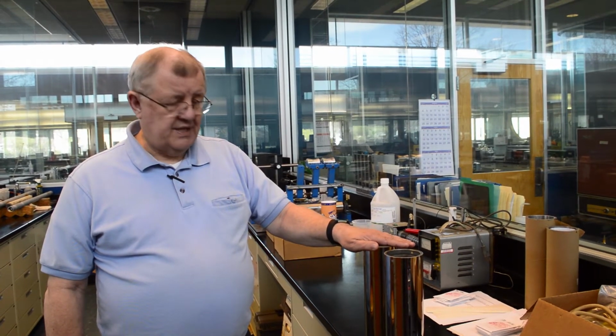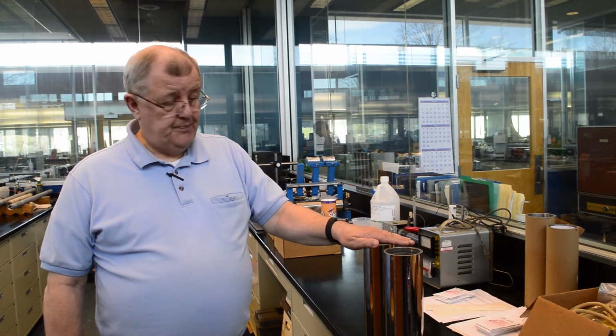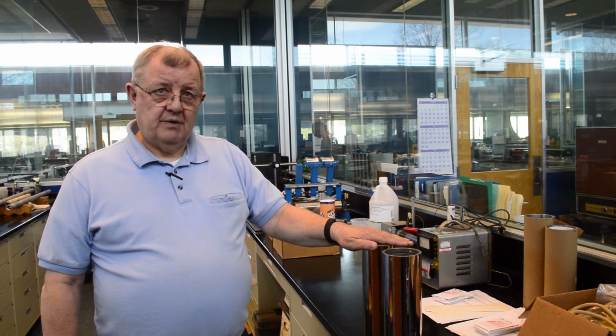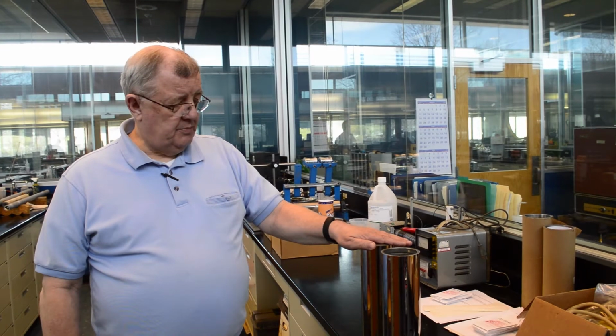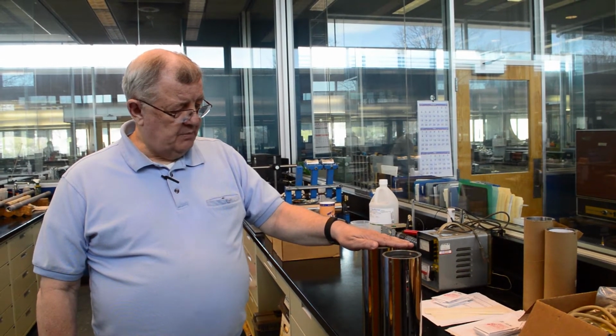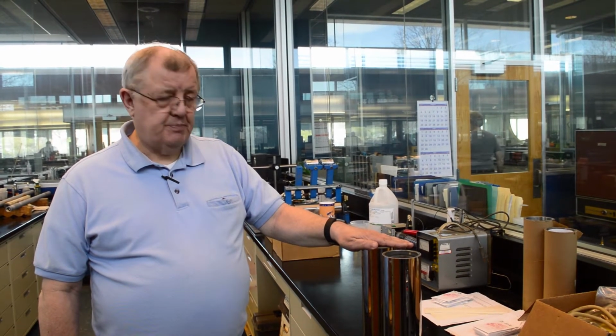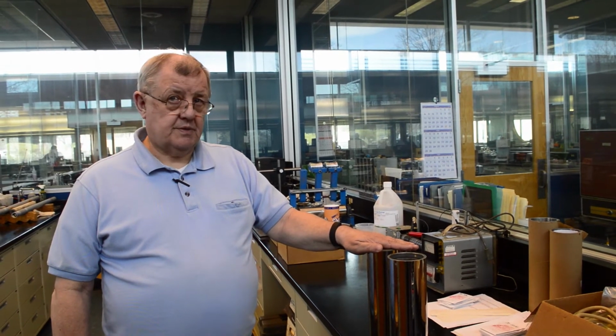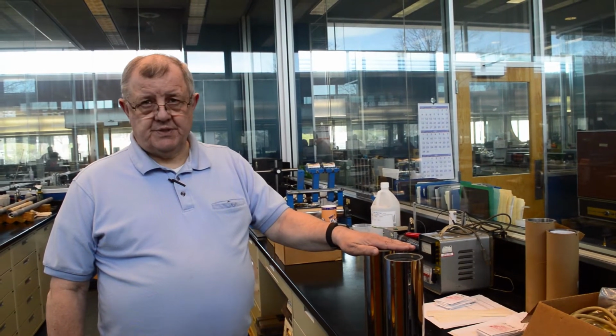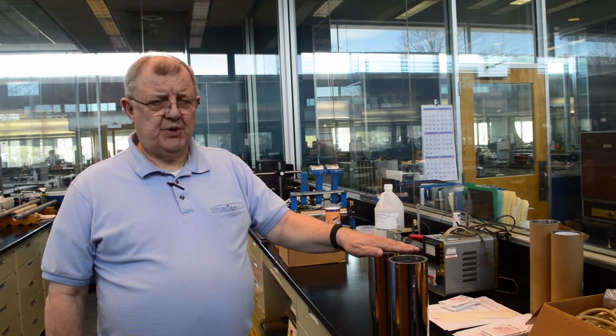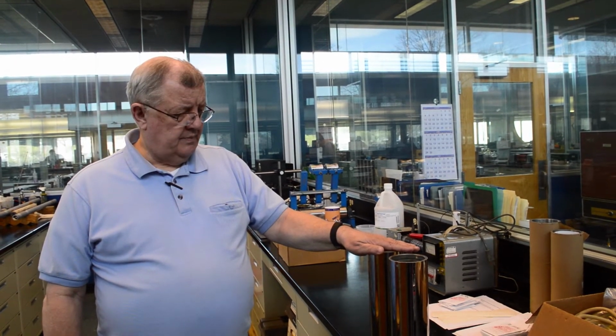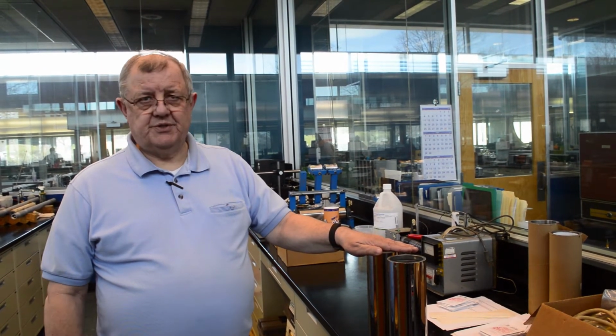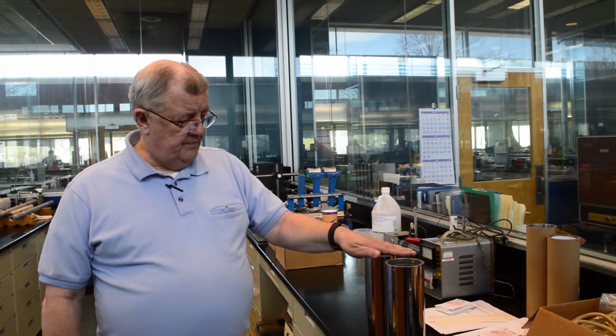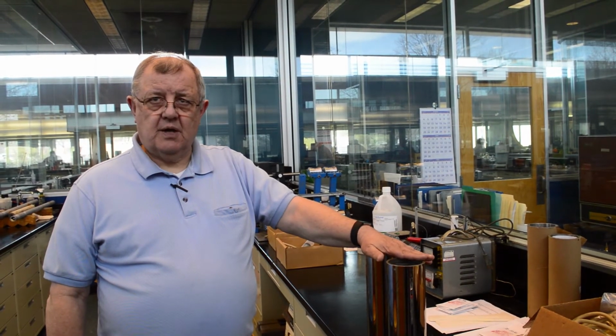Chrome Plus is 10 mils. We can make it thicker. It can be reground if it needs to be, if it's damaged or something. The abrasion resistance is up to 2 times what chrome is. It's much more scratch resistant. Chrome scratches pretty easily, actually, and at that point it has to be repolished or whatever. So there are a number of advantages to our Chrome Plus product.